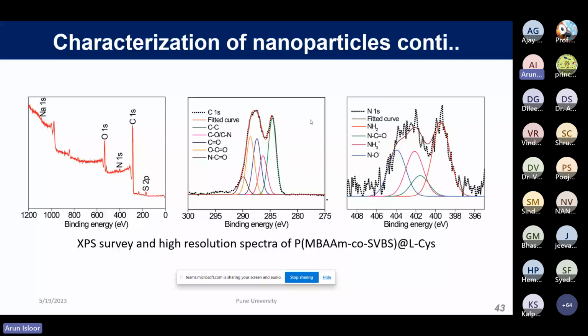And these materials were incorporated into a polymer matrix, and flat sheet membranes were fabricated. So these were the different flat sheet membranes fabricated using the above synthesized materials. The AFM studies showed that wherever more additives were present, the roughness was higher, and the filtration is found to be better on the more rough surfaces. Similarly, the zeta potential and other characterization were done.